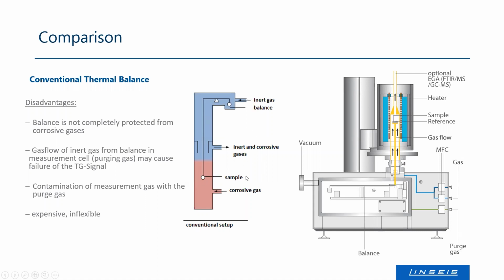On the scheme in the middle, you see the concept. In case of a corrosive gas, maybe you have a corrosive gas around the sample connected to the balance directly, the balance is flushed by inert gas, and somewhere in between you have a mix-up between inert gas and corrosive gas. I'm sorry, this is the other way around than it's shown here, but this is just a schematic drawing. So in the conventional setup, there is a risk of intermixing here. There is a certain risk of corrosive gas going into the balance chamber. It's not really high risk if it's purged properly. Usually nothing should happen, but there is still a risk, and the balance could corrode, the balance could be affected. So it's not really completely protected. The gas flow of inert gas, the protective gas, may cause an influence on the TG signal. It may cause turbulence, convection, whatever.